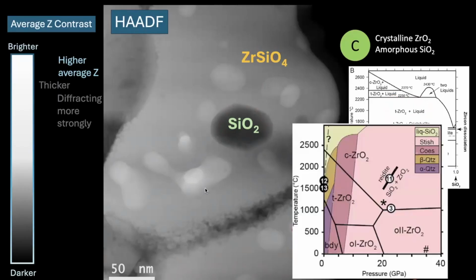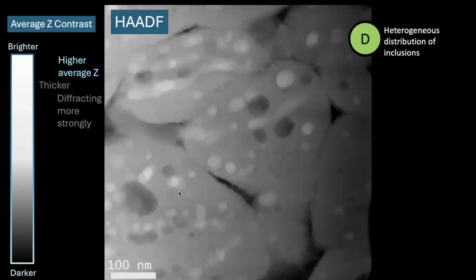But what I need to do is identify exactly what kind of zirconia we have, because that will tell us where on this phase diagram we were, whether we had a monoclinic zirconia, an orthorhombic, a tetragonal, or a cubic, because there are phase relationships between those. And both zircon and Reidite at high temperatures, at different high temperatures, become unstable, and they decompose to zirconia silica mixtures. So then we also have heterogeneous distribution of inclusions.